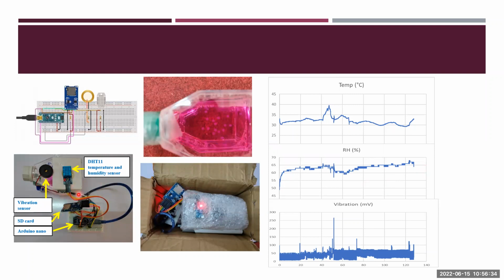And using Arduino, we assembled a data logger to monitor the temperature, humidity, and vibration. You can see the temperature was quite okay, 30 throughout the 5 days. And for a short time, it spiked to 40, which I expect was the time used for delivery in Kuala Terengganu, because sometimes they use motorcycles for delivery and non-conditioned cars or something like this. The relative humidity is quite about 60 to 65 all the time. And the vibration was quite stable, but when the temperature increased, the vibration also increased, which mostly corresponds to the time of the last delivery.